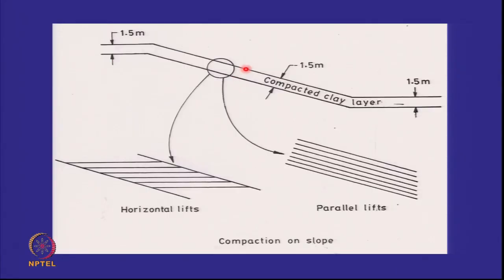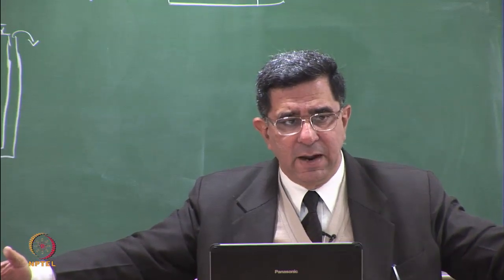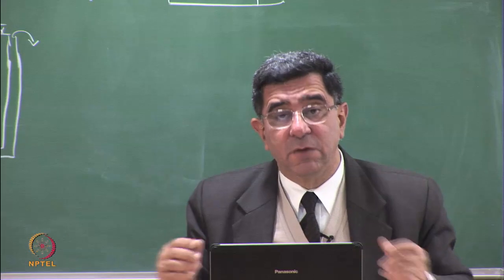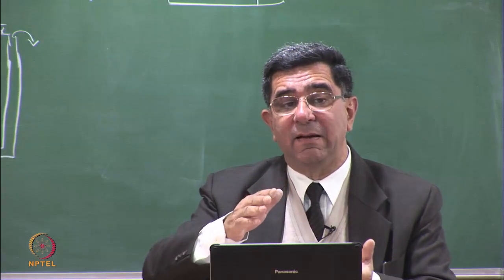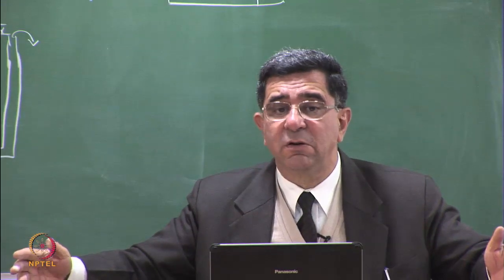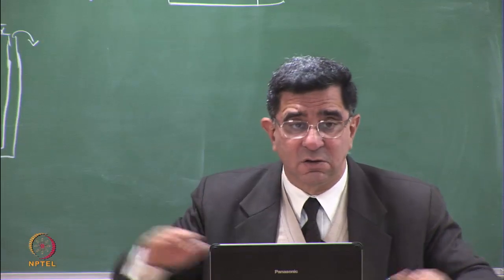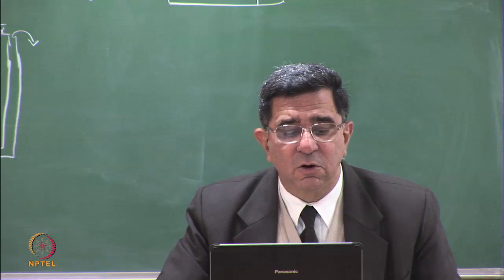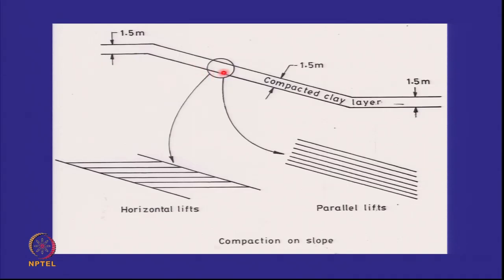So the thickness of this clay is 1 meter. So the question asked is, how can I compact a 1 meter thick layer? My roller is 2.5 meters wide, right? Well, do remember, first you have to use smaller rollers, but this is 1 meter thick. If you look at a 3:1 slope, this will become 2 or 3 or 3.5 meters wide in a horizontal sense. The thickness when we talk about is normal to the slope. So when you cut it horizontally, it will have a much wider thickness and it is possible to do this compaction.